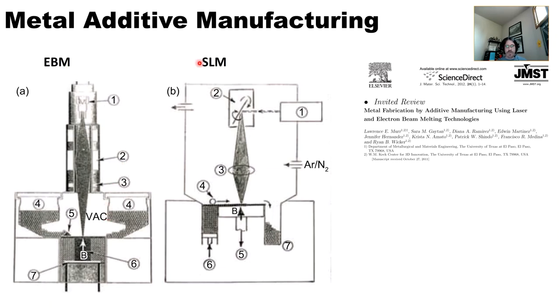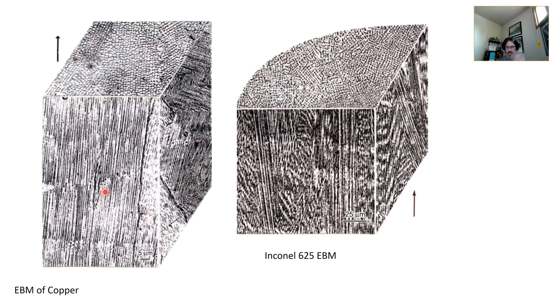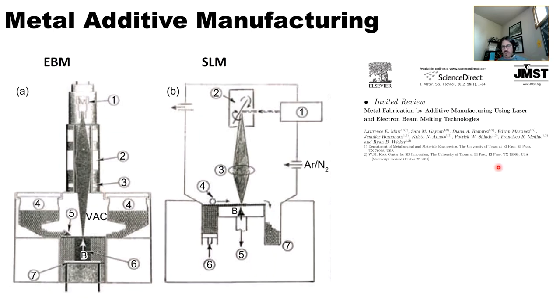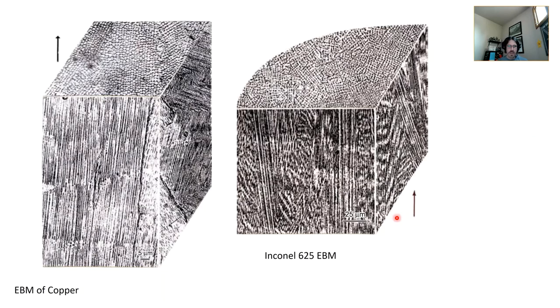Key differences: the electron beam operates in a vacuum; the laser beam operates in an inert gas atmosphere. People have done experimentation purging helium into an EBM during cooling to try to change the microstructure. But how do we observe the microstructure of EBM and SLM fabricated parts? Good old-fashioned metallography. Here are some examples from that article — EBM of copper. Oxygen got into the system and formed copper precipitates, creating an elongated structure. The arrow corresponds to the build direction. Longitudinally you see this columnar alignment; on the top you see how things nucleated; at the very top you see the tops of these columns.